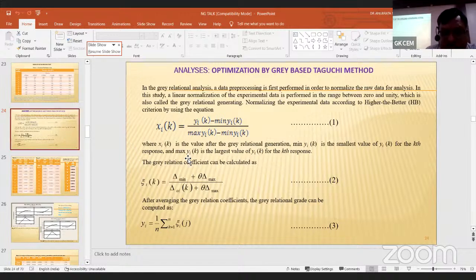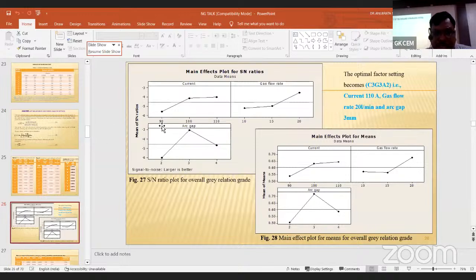So how can they produce a highly reliable, highly qualitative product without getting any actual data that has been obtained by carrying out this type of experiment? Here we perform welding, we perform the tensile test, we perform hardness. Okay, we perform exploratory tests, all is okay. But we get data. What is data? Optimal solution. Here the optimal solution is found by using the gray-based Taguchi technique. It is current 110 amps, gas flow 20, and arc gap 3. At this condition, we found that welding strength is maximum.